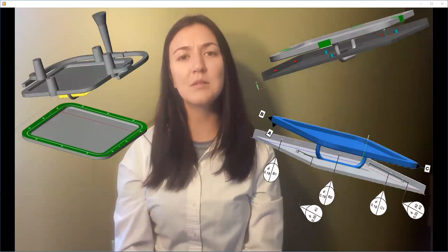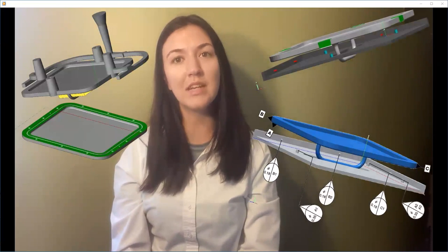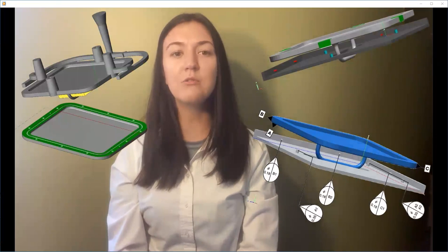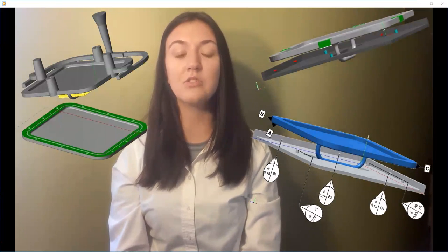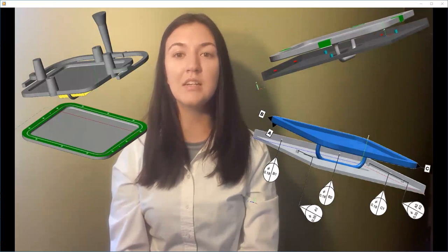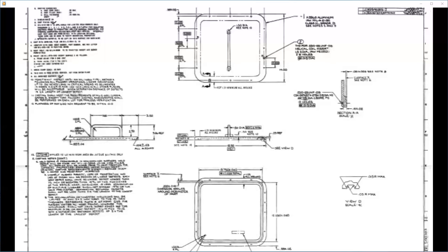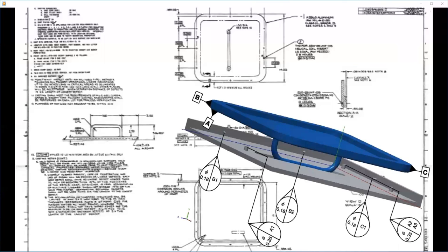Especially important to machine shops are the as-cast surfaces that are used for setup in the first machining fixture, and sometimes part of the setup targets for a second machining fixture. Those as-cast setup features should be datums in the design of the casting, and those features should have datum targets defined on them. For legacy casting 2D drawings, those datum targets are probably not defined, and the metal caster and machine shop must define those targets in advance before anything starts.